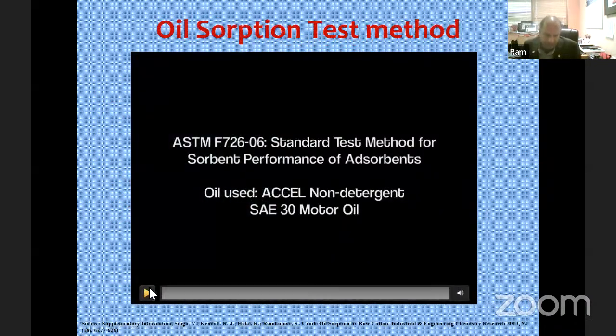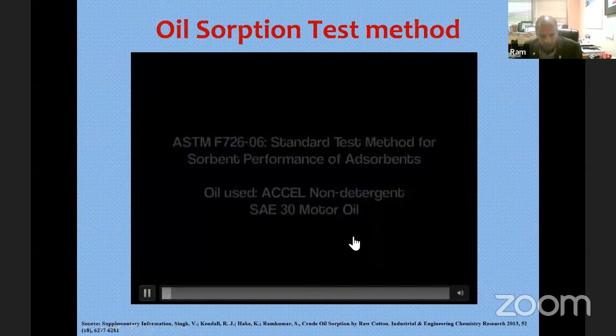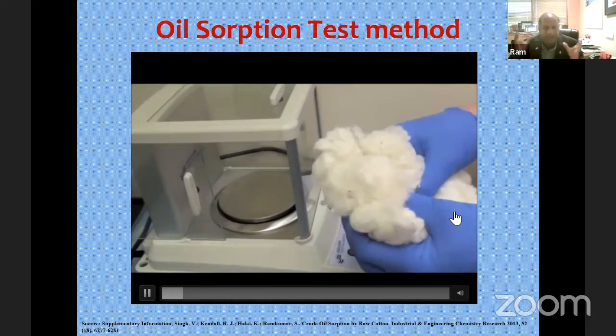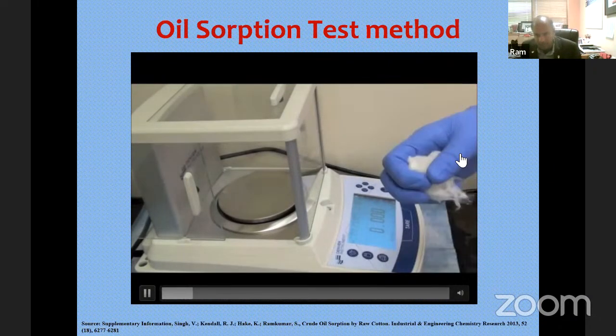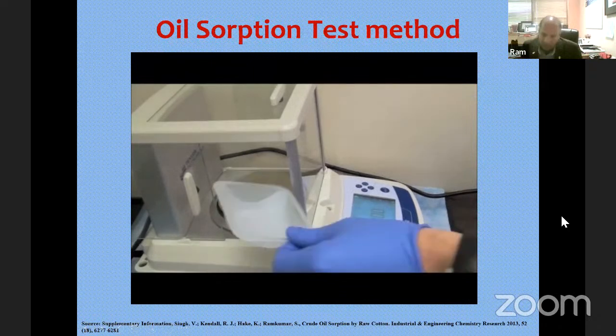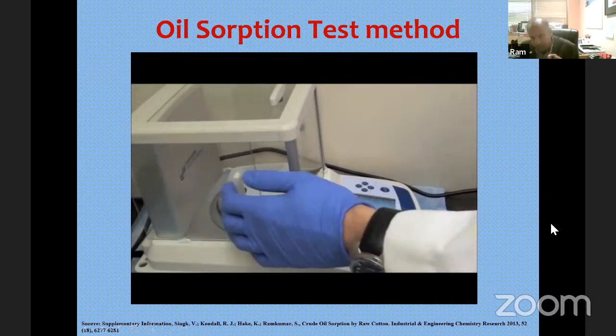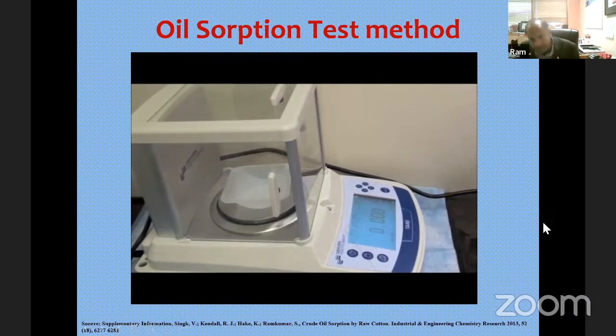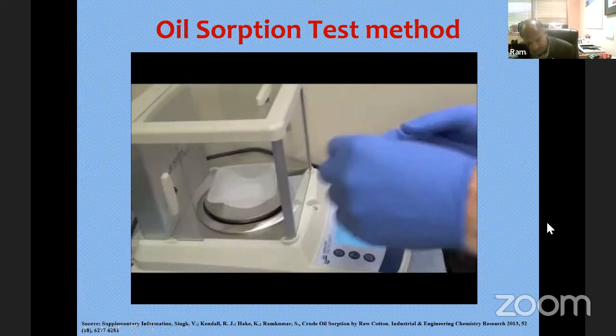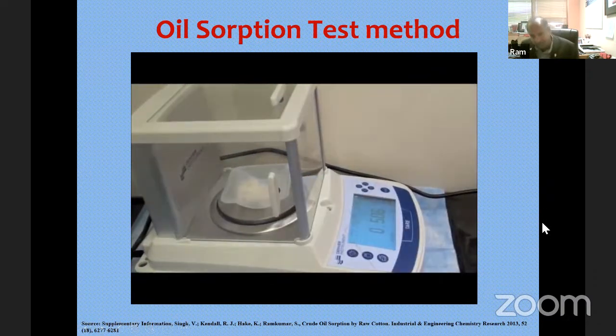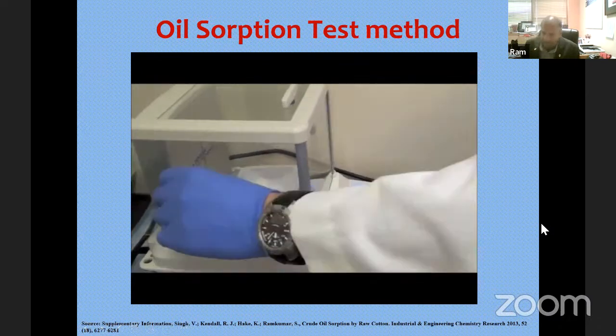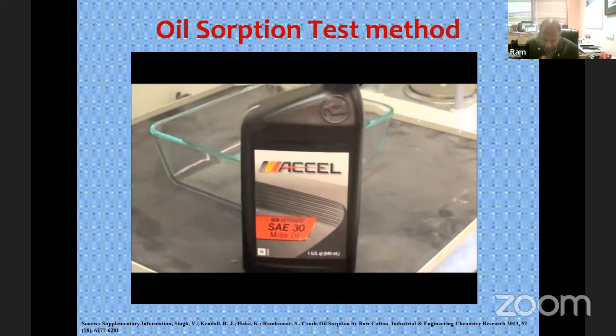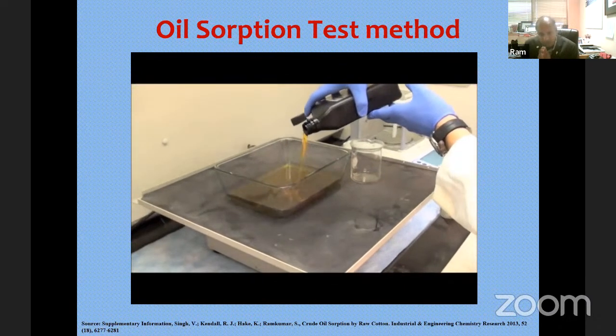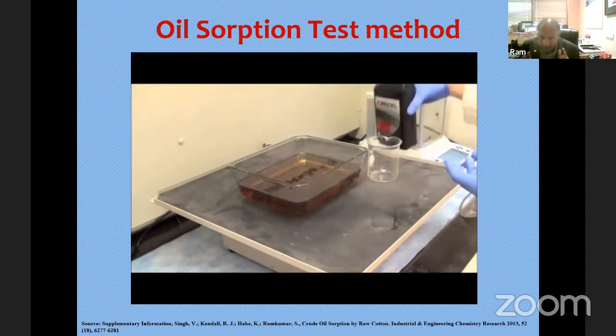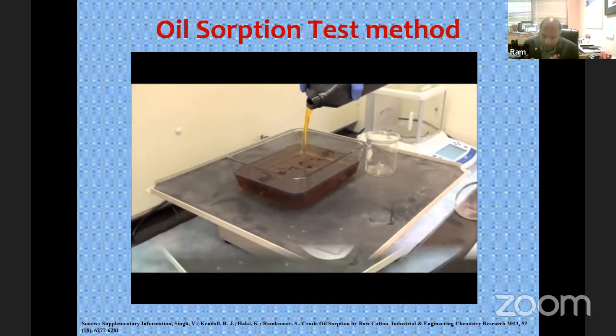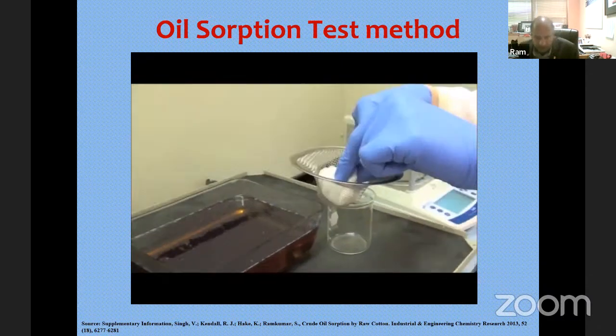And this is the method we did. Again, I'm trying to use some video. So this is a typical non-absorbent, non-water absorbent cotton. And then we take a handful of that cotton, which is based on ASTM method, and then we measure the weight of the cotton and then put it in oil. When you put it in the oil, what did I say? This should not sink, but it should simply float. Just kindly watch the video.